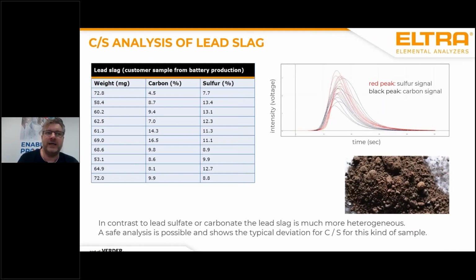And here you have a wide deviation of carbon and sulfur. For example, you're starting with 4.5% of carbon up to 16.5% of carbon. And on the right side, you see the sulfur results, which are widespread from 7.7% of sulfur up to nearly 14% of sulfur. For me, it was a little bit strange to send these results to the customer, but for them, it was quite okay. It just should give you an overview analysis of this kind of samples and maybe give an idea what is the maximum content of the sample.